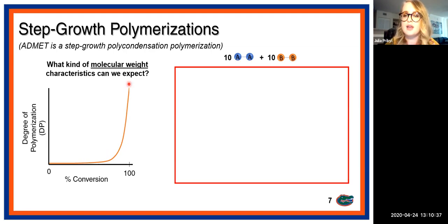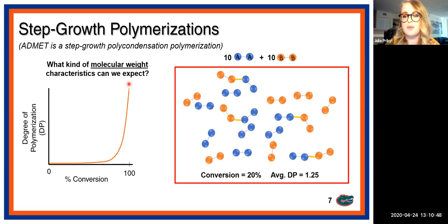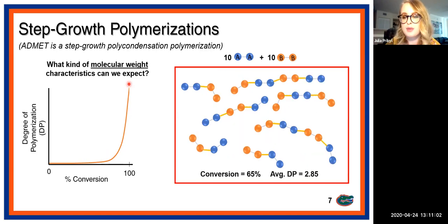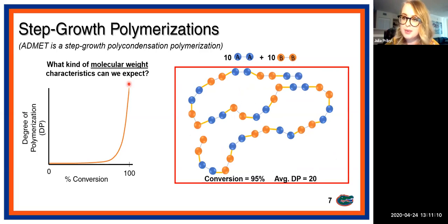So imagine that we have 10 molecules of an AA type monomer and 10 molecules of a BB type monomer, and A and B react together to form a bond. So at 20% conversion, with the reactions between A's and B's denoted by the yellow bonds here, we have an average degree of polymerization of 1.25. As we go a little bit higher in conversion to 65%, there's not much increase in the degree of polymerization, at about 2.8. So it's only when we get to 95% conversion and above do we start to see what we would consider to be a true polymer, not small molecular weight oligomers. So that's something to keep in mind. This is true to perform a successful ADMET polymerization, that you take the reaction to very high reaction conversion.